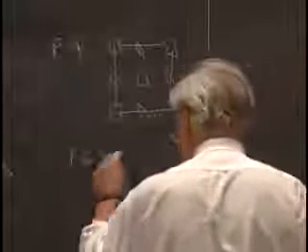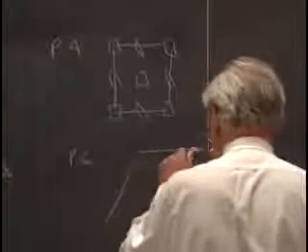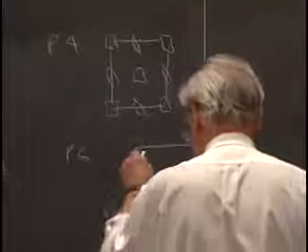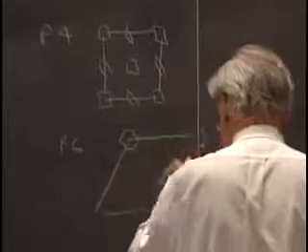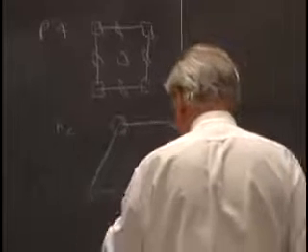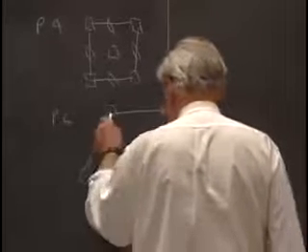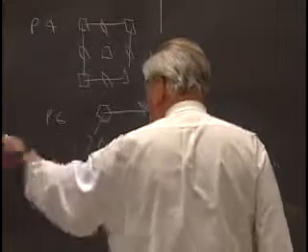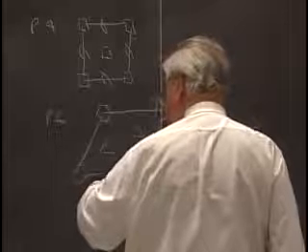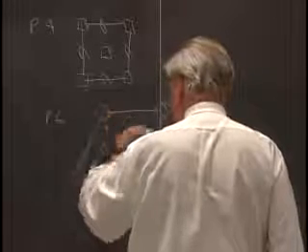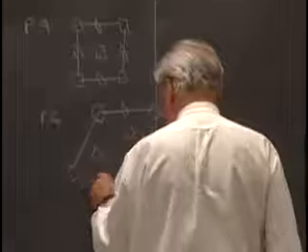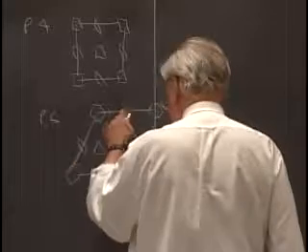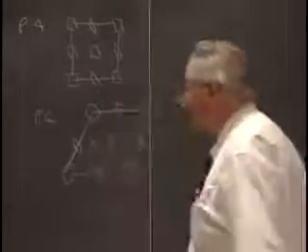And P6, we put that into a hexagonal net. We got six-fold axes that we dropped in at the lattice point only. Nothing else. There's a 120-degree rotation at the lattice point, and that gives us the threefold axes that are present in P3 as well. And there's a 180-degree rotation contained in a six-fold axis, and that gives us the twofold axes in all of the locations of P2.